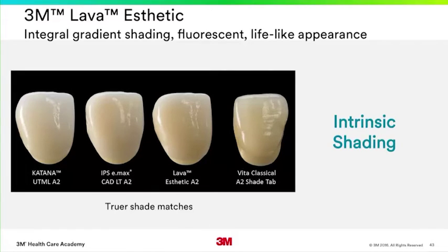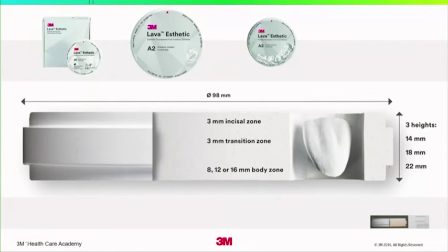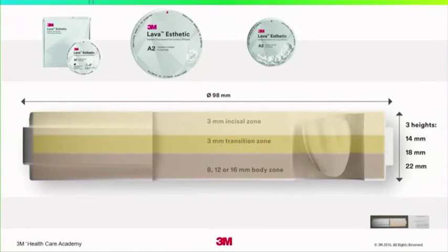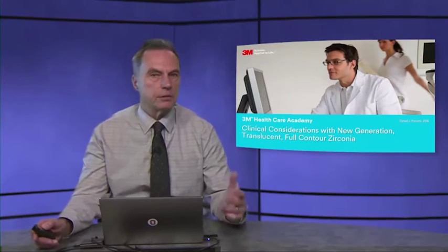This material has intrinsic shading actually built into it, and you can see an indication here by looking at the shade tabs. Very closely it approximates what we typically associate with the standard for shading. The puck is turned sideways here. It's built into a number of incisal zones, so the thickness of the puck actually varies. In this particular case, it could be an 8, 12 or 16 millimeter body zone. And if you'll notice, the shading is intrinsic such that the technician can take this to-be-milled restoration and position it within the gradients to get the maximum effect of the gradients, giving it a more vital appearance and potentially eliminating the need for tints, which eventually wear off.